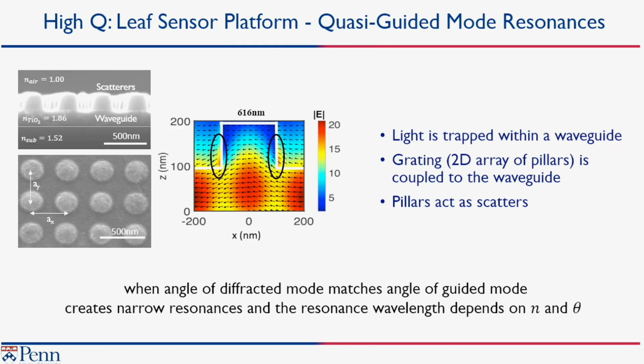And why is that? This is where we get the high Q from: if you have this residual layer, that residual layer acts as a waveguide, and now you generate what are known as guided mode resonances. So the idea is that we have these patterned structures. Those patterned structures will scatter the light into the waveguide. The light then gets trapped within that waveguide structure. You can also think about it as a selectivity in Q, right? You basically have to match the diffracted modes to the resonances that can be supported within the waveguide structure. And so these structures give us high Q resonances.